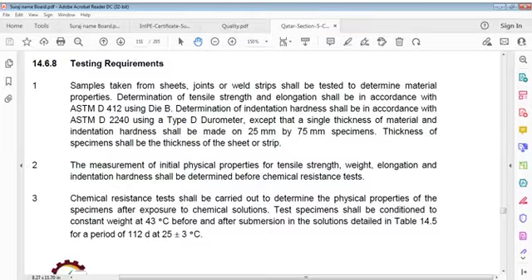Measurement of initial physical properties for tensile strength, weight, elongation and indentation hardness shall be determined before chemical resistance tests. Chemical resistance tests shall be carried out to determine physical properties of specimen after exposure to chemical solutions. Test specimen shall be conditioned to constant weight at 43 degrees Celsius before and after submersion in solutions detailed in table for a period of 112 days at 25 plus or minus 3 degrees Celsius.